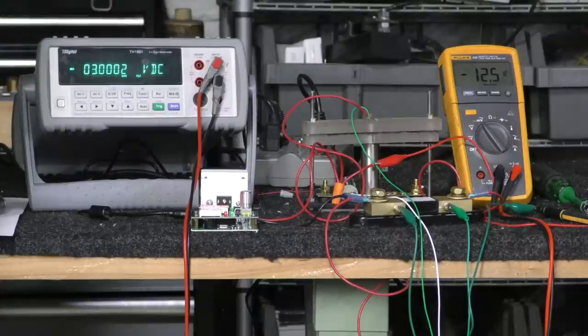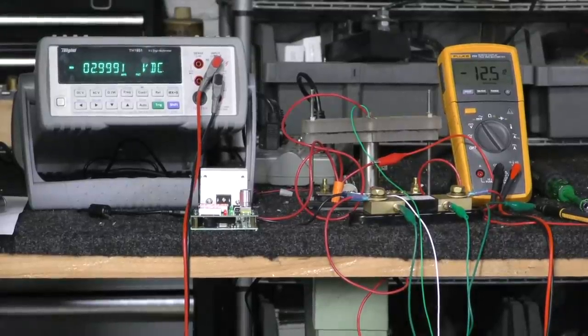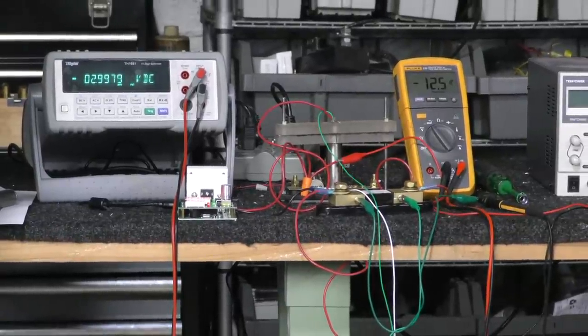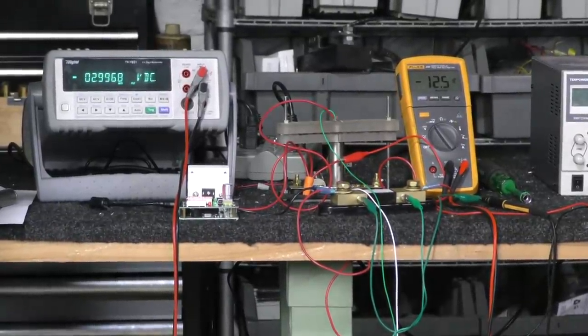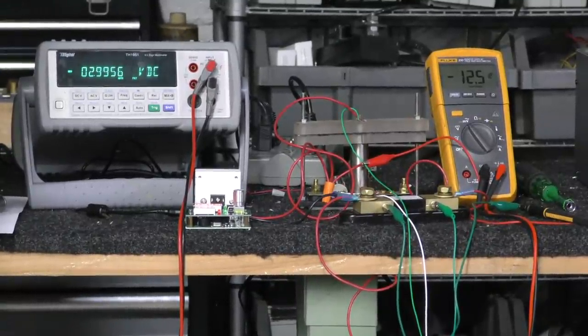Okay, we're coming up on 3 volts, and we're at 3 hours and 18 minutes at 3 volts. We have quite a bit less than 5 amp hours going. That's under the 1.25 amp load. And we're going to let it go on down to 2.8 volts and cut it off there. And then we will revisit this and remove the load and see what our voltage springs up to. But the classic way of doing this is to start at 4.2 and drain it down under load to 3 volts. But I do see some people measure to 2.8. And so we'll do that too.